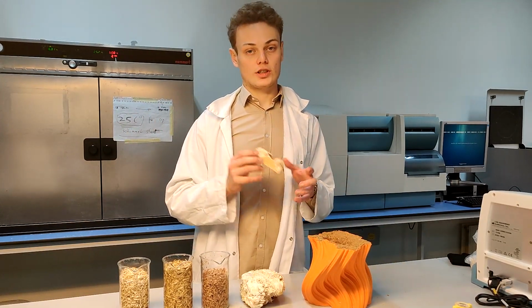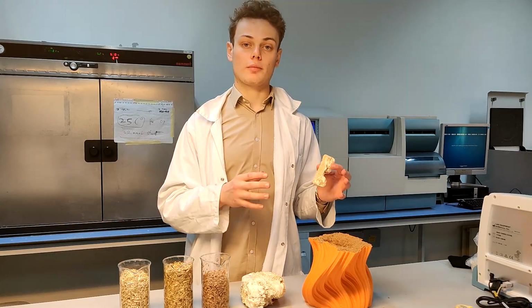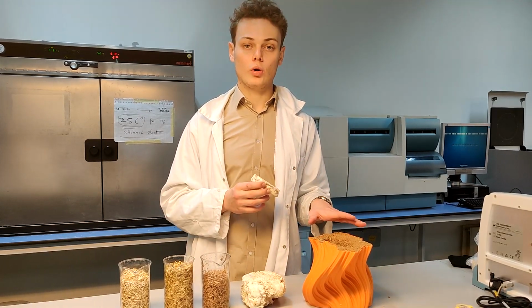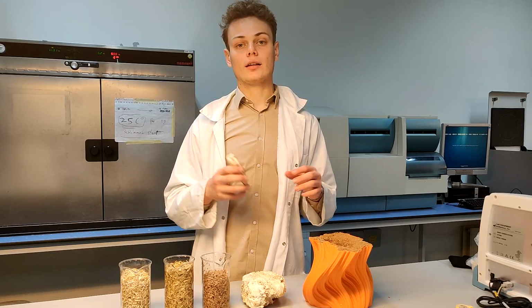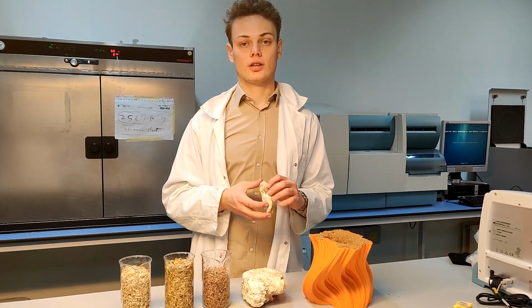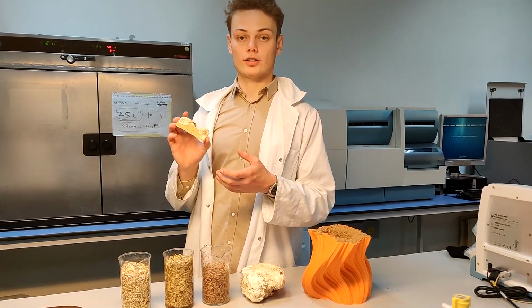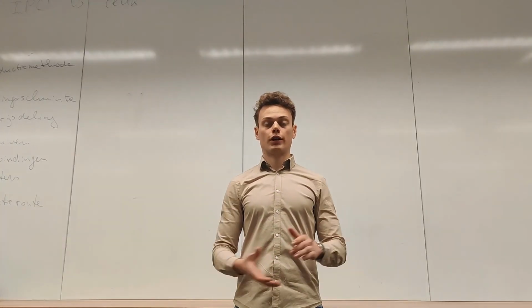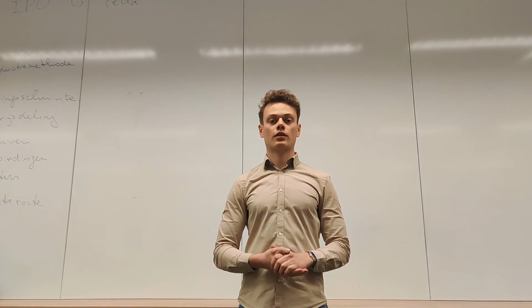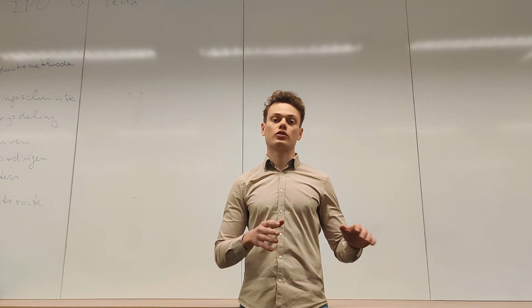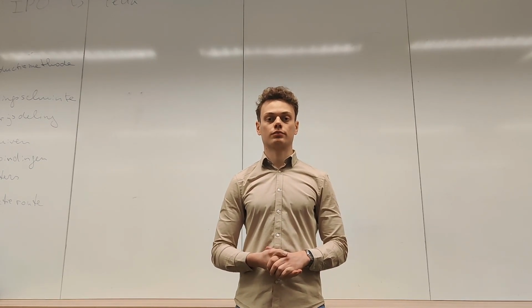Once this has been finished, it is very important to dry the material. And so we put the mold into an oven and we bake it at about 200 degrees. This results in our final product. Great. Now Celine will tell us something about the further research we did into mycelium as a material.